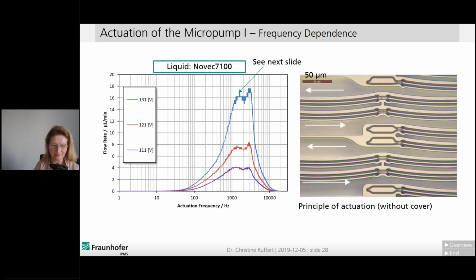Here are some results from the lab, as I promised to show you later on. I told you at 140 volts we have 20 microliter per minute. You see at 131 volts we have about 18 microliters. So this is corresponding. And we see the flow rate dependent on the actuation frequency in hertz, on a logarithmic scale for 3 values of applied voltage. The flow rate increases with the applied voltage, and this is done for the dielectric liquid Novec we use for our investigations on liquid pumping in the lab. I will come back to this peak here, which is at 1.5 kilohertz, on the next slide.